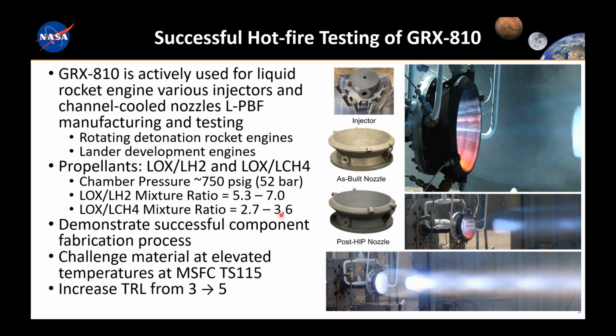And one of the messages that I think you'll see later as I go through these slides is that the material holds up very, very well in these environments, even when we push it outside of some of the nominal conditions. Like I mentioned, it's really critical to take the material and these components through the entire fabrication process. And I'll highlight that in a couple slides here. And really, the main purpose of all this testing was to increase what we call the technology readiness level, or the TRL, from just a lab environment, putting it in the actual environment. So, where we're at today with GRX 810 is we're at a minimum of a TRL 5.